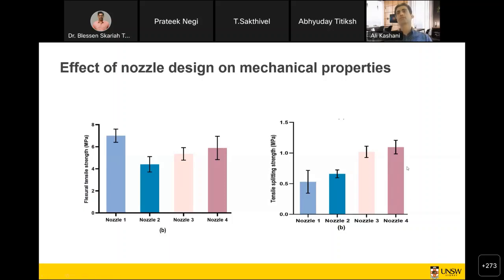For example, with nozzle 4, which is the rectangular nozzle with the highest aspect ratio, the bonding between the layers is very high, and for that reason, when we do the tensile splitting strength test, where we apply the force at the boundaries of the 2 layers, we get the highest strengths. The size of the samples is the same, so it's not an effect of the size, but the bonding is much better.